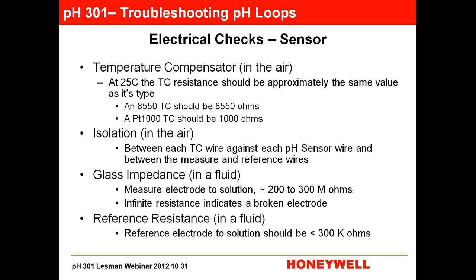If you're using a glass measuring electrode, you can check the glass impedance. The impedance on the electrode when it's in the solution should be somewhere between 200 and 300 megohms. If you're using one of our HB sensors, you're probably going to be up around 600 megohms because it's very high impedance. If you get infinite resistance, then you probably have a broken electrode. If you get very low resistance, you've lost a lot of the face of the sensor. Maybe you've got a process that has occasional hydrofluoric acid in it or something, and it's breaking down the glass. It's getting thinner and thinner. So you can look at the impedance. And again, you just put your multimeter on the measuring electrode wire and then drop the other end right into your process fluid, or your beaker of process fluid.